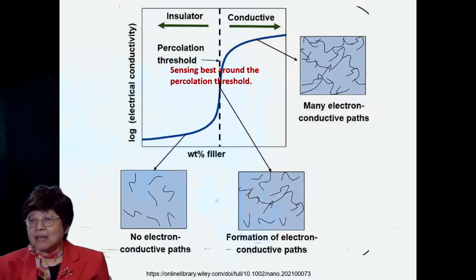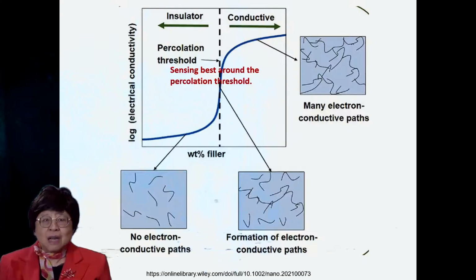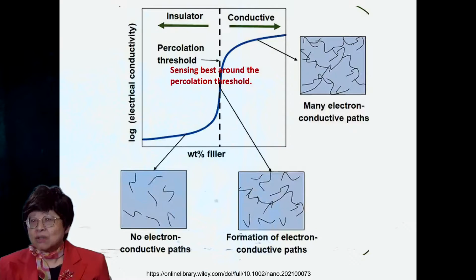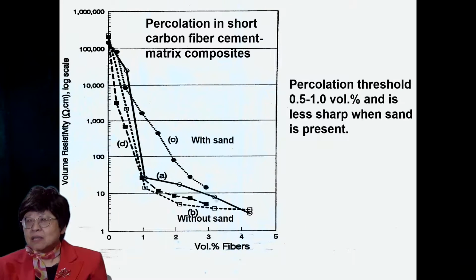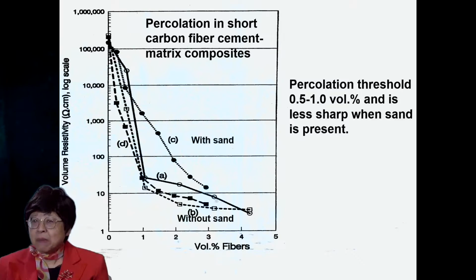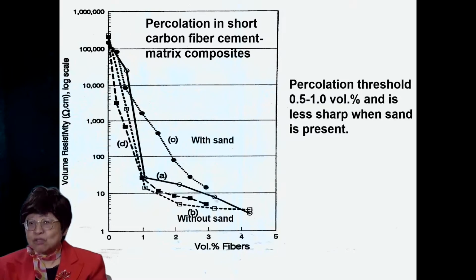The conductivity increases with increasing conductive filler content, in this case, short carbon fiber content. When it's above the percolation threshold, you have touching between the filler units, and so it's conductive. And the sensing is best if the composition is near the percolation threshold. And this is the plot of the resistivity versus volume fraction of short carbon fiber, and it does drop by orders of magnitude, and the drop is sharper if you have no sand.